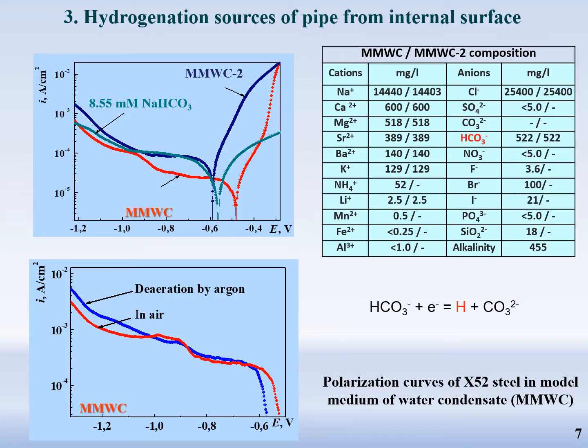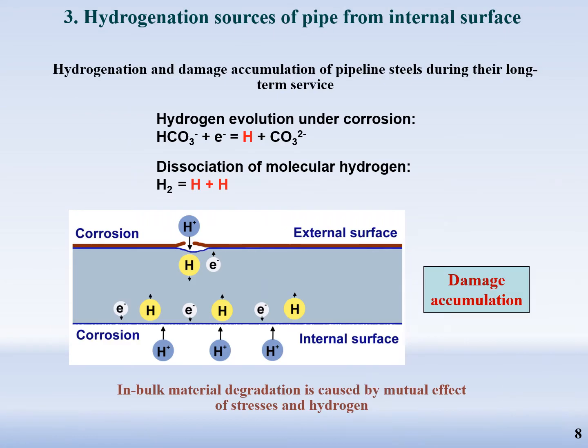Our preliminary study showed that the model medium of water condensate on the internal surface of gas pipelines has served as a source of hydrogen due to electrochemical corrosion. The same situation should also be in the case of gas-hydrogen mixture transportation. Then, hydrogen in atom state, evolved as a result of electrochemical reaction and molecular hydrogen dissociation as well, can be absorbed by pipe metal in atom state, which can migrate via the pipe wall.